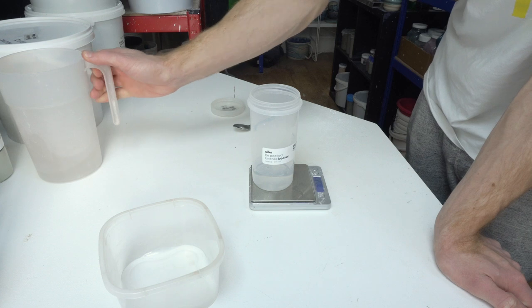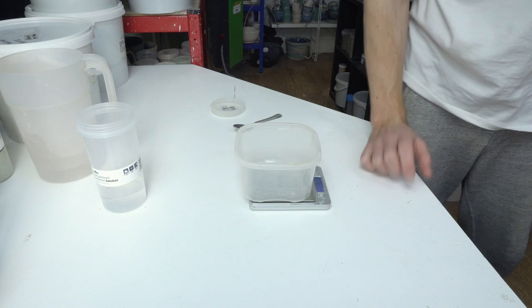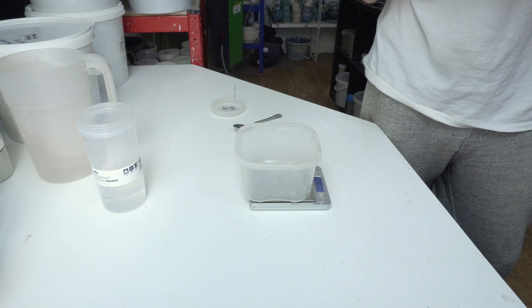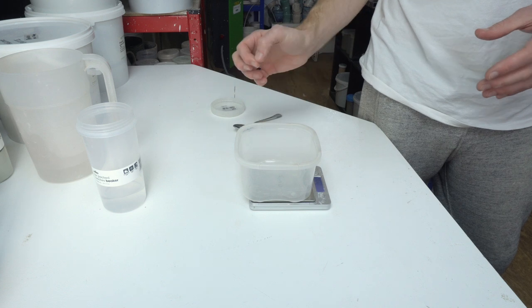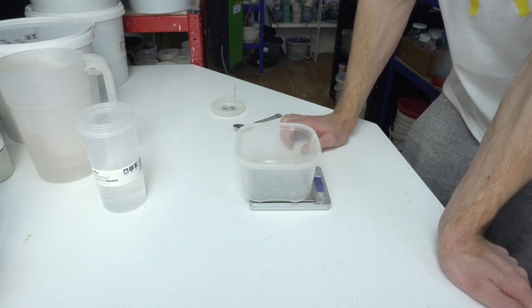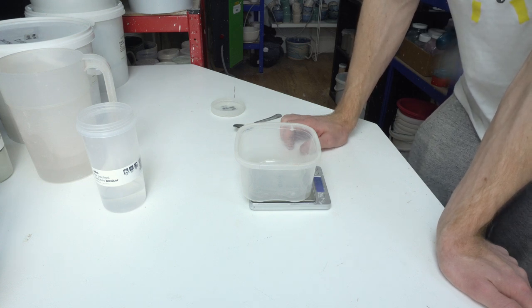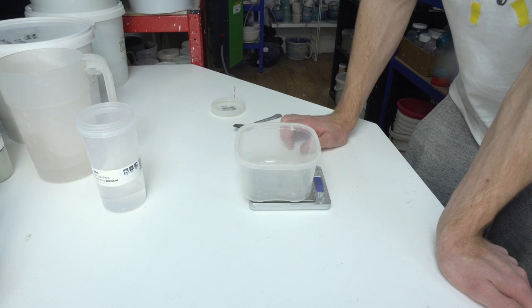But I figured out a way of doing it myself, and it's basically by sintering a glaze. So sintering is the equivalent of bisquing. What I do is I mix up a glaze, dry it out, and then break it into chunks and fire it in a bisque firing. And if you get the chemistry for the glaze right to match your bisque firing temperature, they sinter into chunks that are still porous, they haven't melted, which means they don't fuse together, but they are like bisqueware.